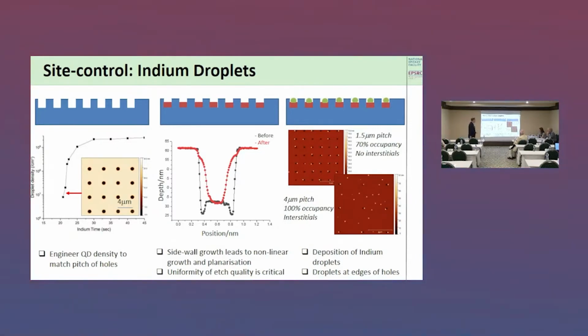That's fairly good, actually. When we go to the 4 micron pitch that we show here, where you've actually got a lot longer distance for the indium to diffuse into the holes, we actually get about 100%. We get 100% occupancy in this case, but we do get quite a lot of interstitials here. So somewhere between these two is an optimum, and as long as that optimum allows us to do optical measurements, we're happy with that.